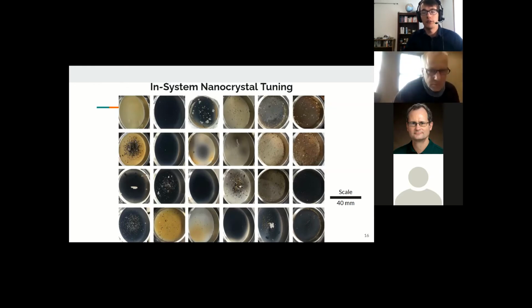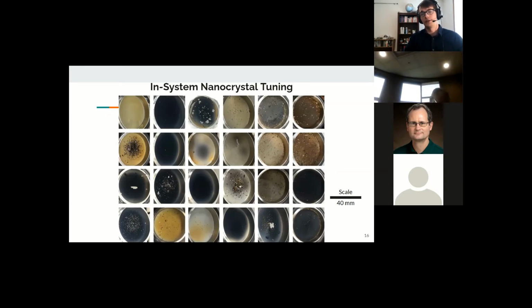As can be inferred from the velocity equation that I showed earlier, an increase in flow of the gas through the reactor will result in an increase of velocity through the reactor. They're linearly dependent on each other. Therefore, a decrease in the pressure of the plasma, all else being equal, will also increase the gas velocity through the plasma. And the faster the gas moves through the plasma, the shorter the residence time. Thus, these tuning parameters should allow for size tuning of the nanoparticles. The reaction gas, the hydrogen that we add, allows for tuning the carbon content of the nanocrystals, which tend to be either carbon-rich or silicon-rich.